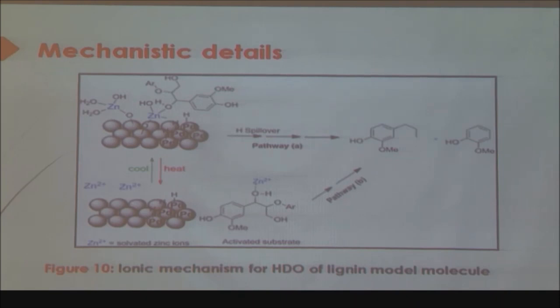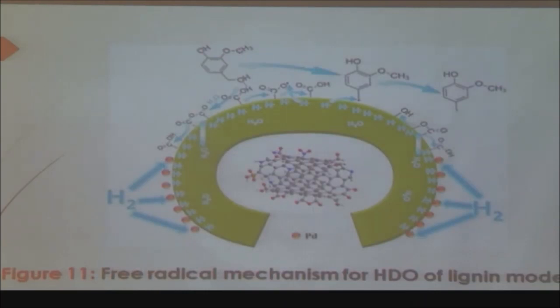So this was the proposition that we propose, that if people are using some ions, because there are a lot of catalysts that use ions, and that ion somehow promotes the heterolytic cleavage and the reaction is progressing through the ionic intermediate. Whereas when you are using nanoparticles, metal in zero oxidation state, for example, nickel carbon, platinum carbon. All of you must have studied the mechanism of hydrogenation. So what is involved in this reaction? Free radicals, it is proposed. Both the cleavages, homolytic and heterolytic, are proposed, but mostly it is free radical which is generated.